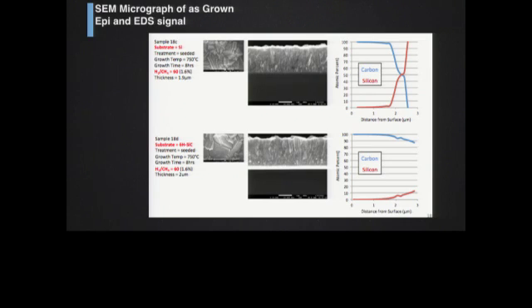We also have studied the interface. One of the things that we were really interested in is seeing what kind of interfaces we can make. This is with silicon, and this is silicon carbide. With the silicon, we get a very, very sharp interface between the diamond and the silicon. However, with silicon carbide, we get this gradual sort of interface, and that's primarily due to some graphitic compound that seems to build up at the interface of the diamond. This is diamond up here, and this is the silicon carbide.